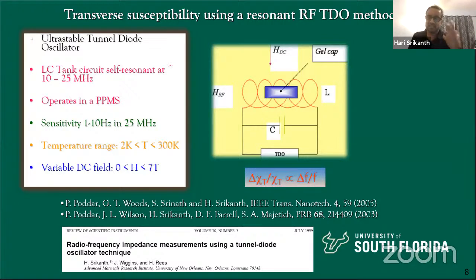field of magnetic anisotropy, we were one of the first groups that developed a very sensitive resonant technique for measuring the so-called transverse susceptibility. We do this measurement in a slightly different way. This is a resonance circuit. And again, I don't have time to describe this, but essentially because it's high frequency, it's done at megahertz. So essentially it's like an FMR measurement, ferromagnetic resonance measurement. And from that, we can extract the change in the transverse susceptibility.